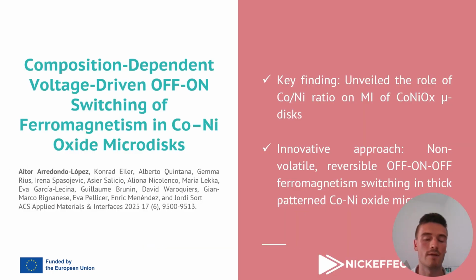To introduce the most important outcomes obtained by the UAB related to the goals of the NICKEFFECT project, the first work, titled Composition-Dependent Voltage-Driven Off-On Switching of Ferromagnetism in Cobalt Nickel Oxide Microdiscs, unveiled the role of cobalt-to-nickel ratio on magnetoionics of cobalt nickel oxide microdiscs, thanks to non-volatile, reversible off-on-off ferromagnetism switching.